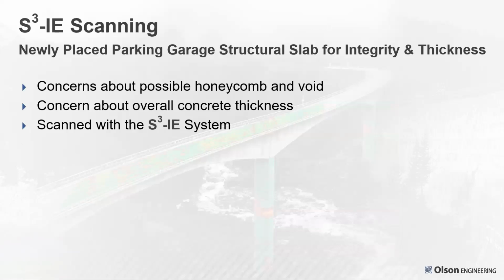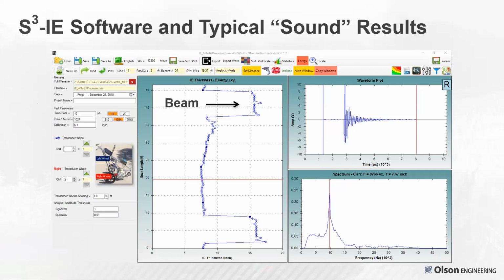My next example is another parking garage. This is a newly placed parking garage slab. So rather than looking for delamination damage or other issues, in this case, we're looking for concerns about possible honeycomb and void in the slab. They are also worried about overall concrete thickness, but primarily they're looking for issues from the placement, the original placement. So we scanned this with our S-cubed unit.